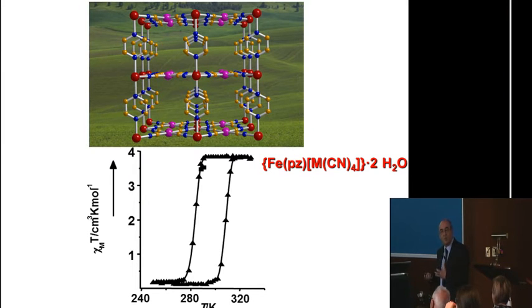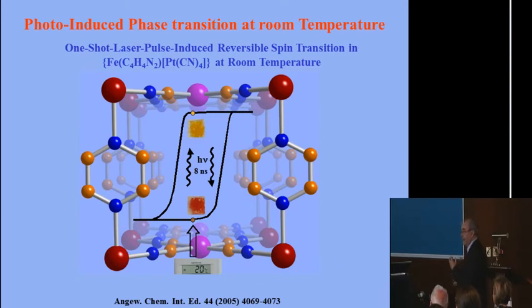So then room temperature is very important. Why? Because if we want to make applications, we need systems which work at room temperature. And in this system, you have first the crossover at room temperature here, and you have the hysteresis at room temperature. That means that we can deal with the integration of the system into devices to use the hysteresis or the switching in order to have devices. So then we wanted to switch these systems by light. Okay? We wanted to switch.